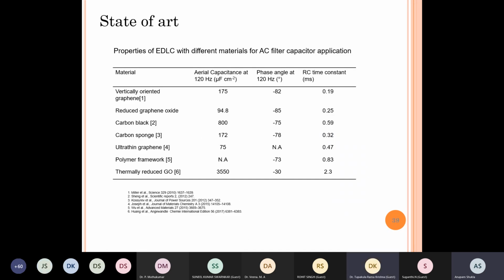So if you look at the state of the art in research papers on EDLC, which are used for kilohertz frequency response supercapacitors, these are all graphene based. Okay, they're all graphene based. This is the areal capacitance at 120 hertz. That becomes a characteristic feature now. Here are the phase angles. Closer to -90, the better the capacitive behavior, and the corresponding RC time constants.